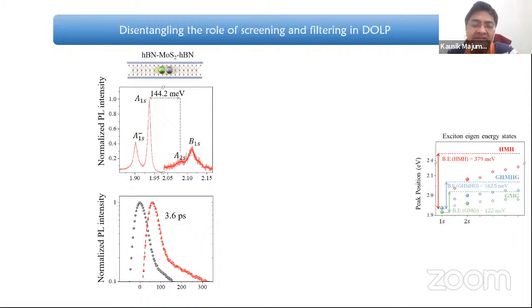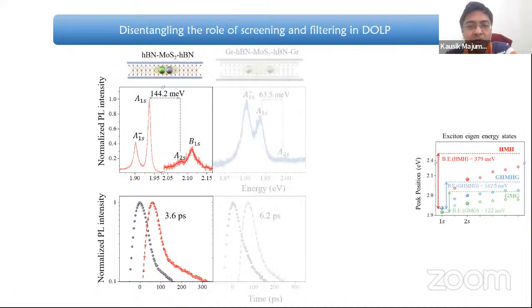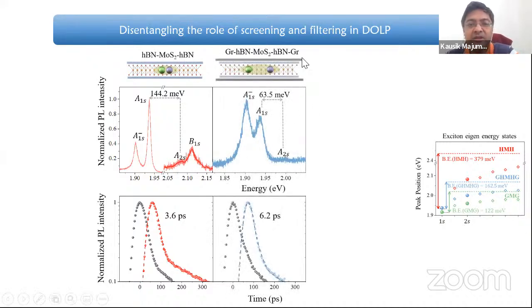So what we did is look at exactly how this screening versus lifetime is playing a role. In the hBN encapsulated MoS2, we measured the 2s state and 1s state separation, and we find it's about 144 millielectron volt. And then we solved the Bethe-Salpeter equation and found out the total binding energy of the stack is about 379 meV. We also did the corresponding TRPL, time resolved photoluminescence measurement. We found it about 3.6 picoseconds. Now we did the same thing on the graphene and hBN encapsulated stack.